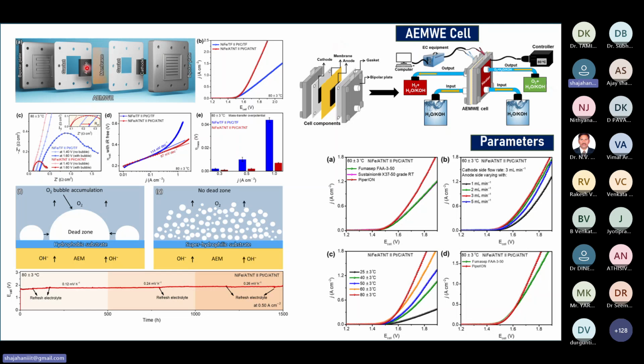So we placed our NiFeNT3 as the anode and commercial Pt/C as the cathode, and made this AEMWE setup. On the ATNT substrate based setup, this red one we consider the hydrophilic based setup. The same catalyst on the TF titanium foam we consider the hydrophobic substrate. When you compare the performance of the AEMWE, we observe that the hydrophilic based one showed better performance than the hydrophobic one.